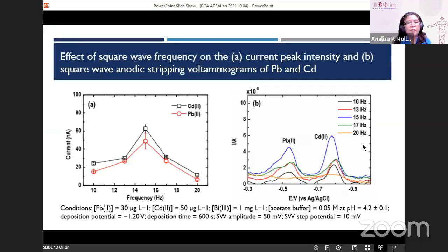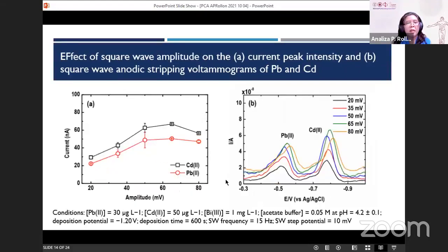And then for the effect of the square wave parameters, like in this case, the frequency, you can see here the current versus the frequency. It is shown here that the frequency is somewhere between 13 and 17, both for cadmium and lead. And also, if we increase the frequency further, you can see that the base of the voltammograms can be broadening. And for the effect of the amplitude,